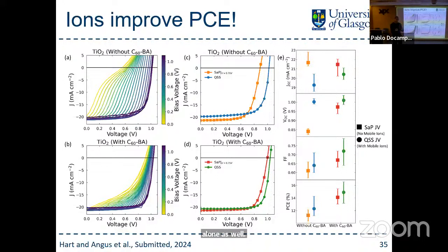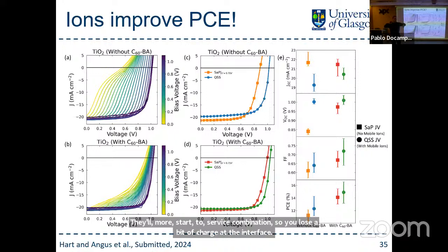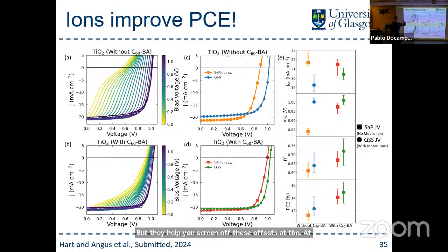They make you more sensitive to surface recombination, so you lose a bit of charge at the interface, but they help you screen off these offsets at the conduction band and valence band with your charge extraction layers, making your cells a little bit more efficient. So they actually help you smoothen out these potential differences at the interfaces, which is a very interesting result. It basically means that ions actually enable us to make better devices. So we shouldn't be trying to get rid of them. We should try to make use of them.